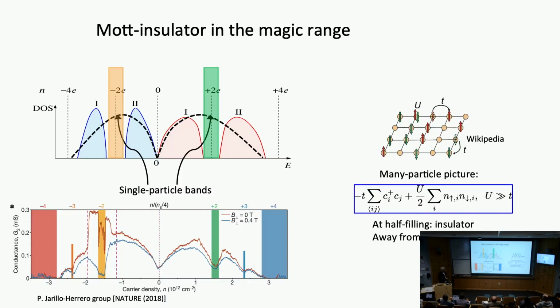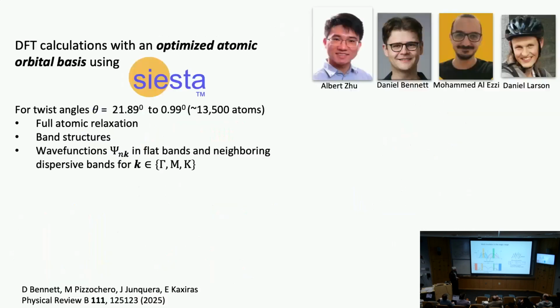And this is what is referred to as Hubbard physics. So you have a situation where you have electrons hopping between different lattice sites. That's the kinetic energy term captured by this part here. But you also have electrons on the same site, labeled by i, with up or down spins, and there's a big energy cost when you do that because of the Coulomb repulsion between the electrons on the same site. So two electrons on the same site have to pay a high price in energy, and electrons, when they are allowed to move around, they gain kinetic energy. That's this contribution. Now, this simple model, if you are close to half filling, that is one electron per site, produces a state that is insulating, and produces this kind of half-filled band with a gap separating the two half-filled bands.